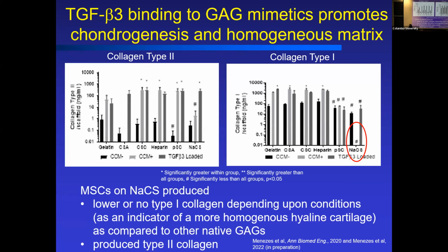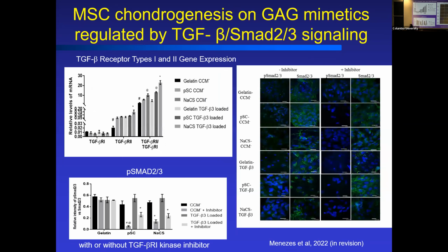fully sulfated cellulose, you got less, or if not none, no collagen type 1. So again, with cartilage, you want to form homogeneous cartilage. That's all type 2 collagen production. You don't want the fibrocartilage, which contains that type 1 collagen. So the fully sulfated cellulose actually promotes that more homogeneous collagen type 2 matrix.